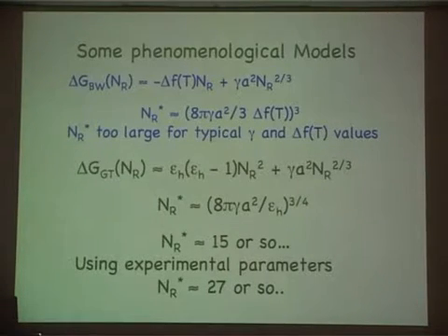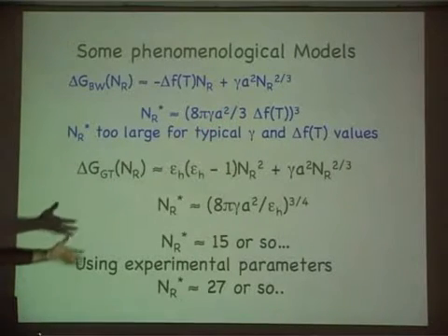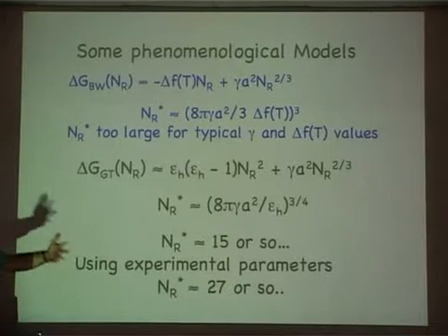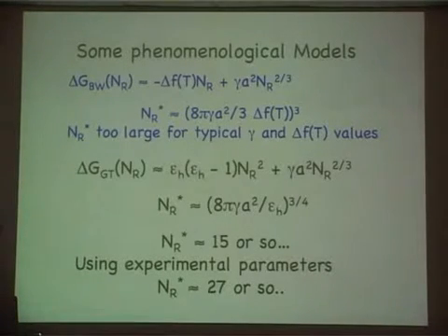Very crude, and this is really not the value that you should actually be putting at all, and this is one of the problems that I'll repeatedly mention is something we don't know how to do. No, it's correct. That's a free energy transfer, and then for that you subtract out the cohesion energy. What's left over is what is done. So it's a little bit more involved analysis, but that's a basic experiment. And people have also even tried Tolman corrections and things of this kind, even for this little object. So remember, these objects are going to be of the order of about 5 to 7 angstroms.